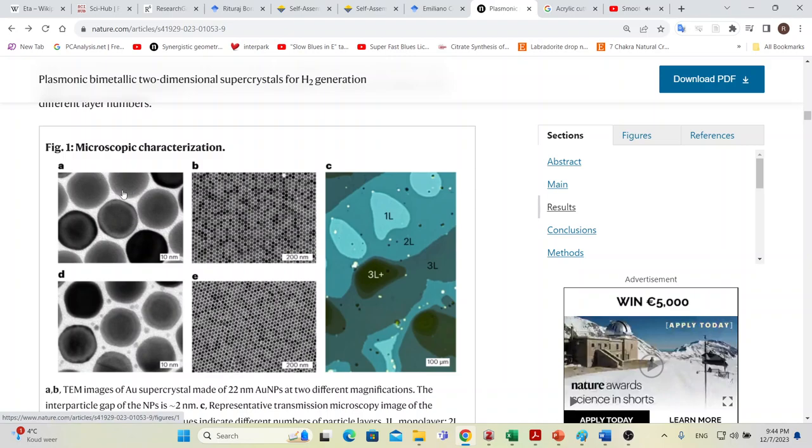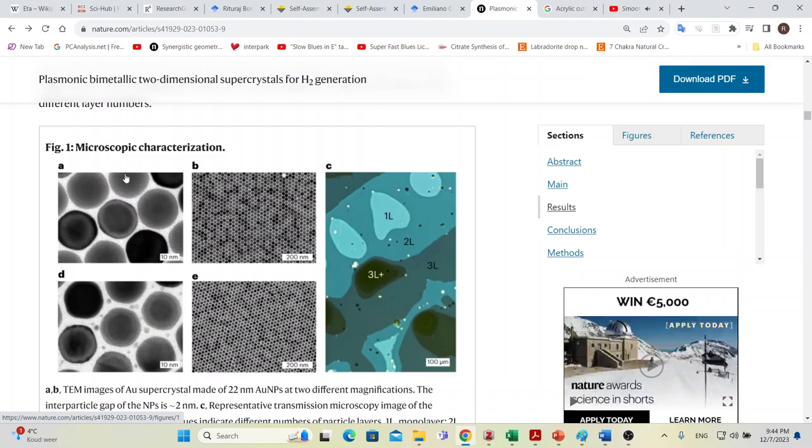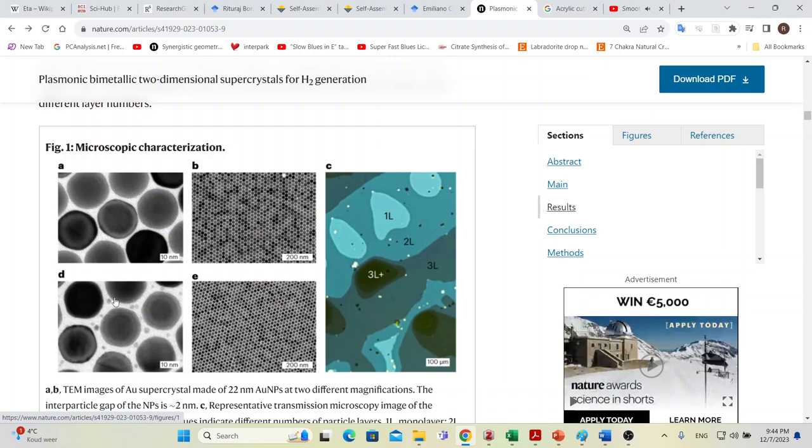If you're into plasmonic nanoparticles or plasmonics in general, then you know that this is called plasmonic coupling. Basically, these gold nanoparticles' optical properties are kind of coupling with each other, so they give a collective optical response together. Due to this collective optical response, there is a light concentration effect in these inter-particle gaps. When the platinum nanoparticles are right there in the interstitial gaps, then we have this enhancement in the reaction.